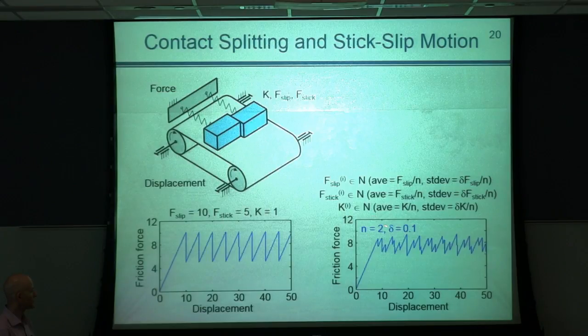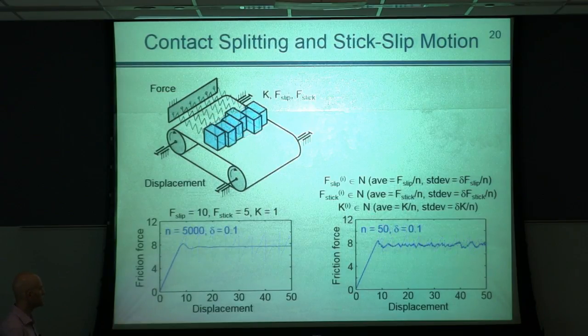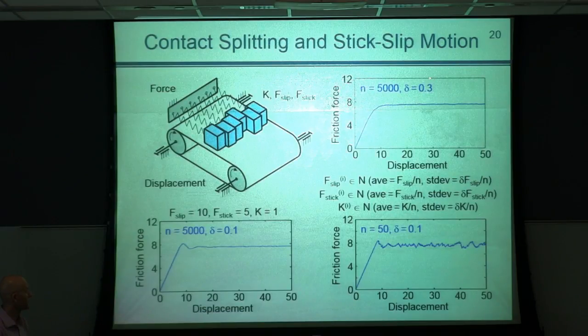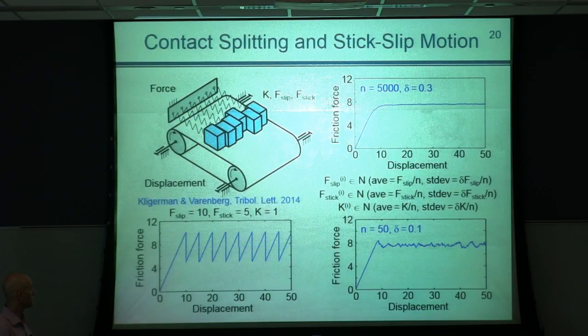And this is what was obtained for just two elements. If we increase the number of elements, these are the results obtained for 50 small blocks or 5,000. Clearly, the sliding becomes much more smooth, and we do not see this sawtooth-like behavior characteristic of the motion of sticky elastomers. And the interesting thing is that if we increase the variance, then the friction force appears similar to the result that we saw on the previous slide. So this very simple toy model allows us to explain the differences between surfaces that possess different numbers of elements, if these elements have some variance in their properties.